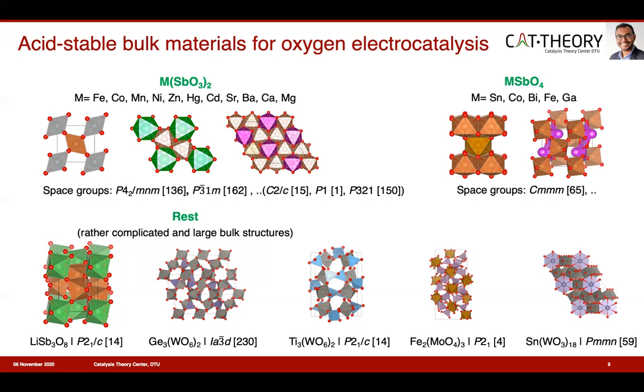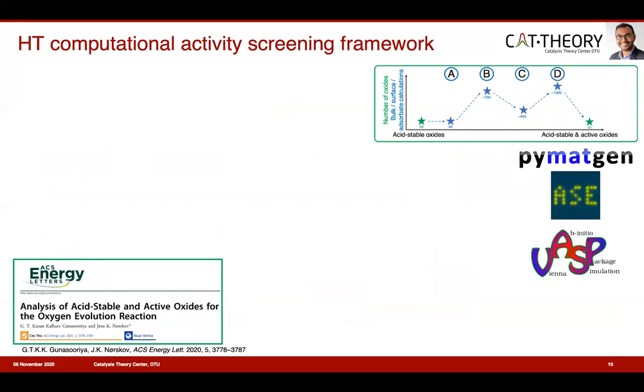This variation of space groups and the number of atoms in the bulk structure of the acid-stable materials indicates the structural complexity and the diversity of the surface models and their active sites. Moreover, for a given material, there are multiple exposed facets with different oxygen terminations, and these facets have multiple unique adsorption sites according to the coordination of the adsorption site. Most of the studies in the past address this complexity by focusing on a specific crystal system and/or a specific facet, usually the most dominant based on X-ray diffraction or XRD pattern. However, it is important to note that less stable surfaces could significantly contribute to the activity compared to the most dominant surface.